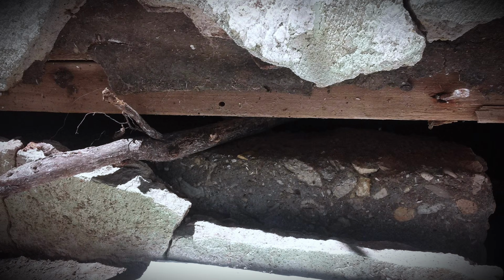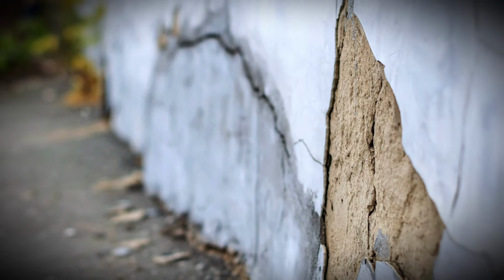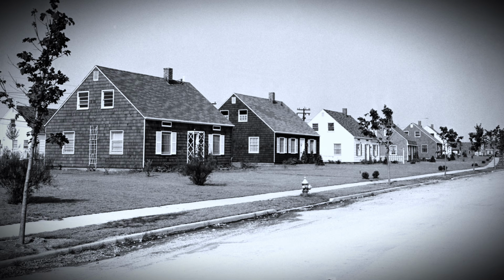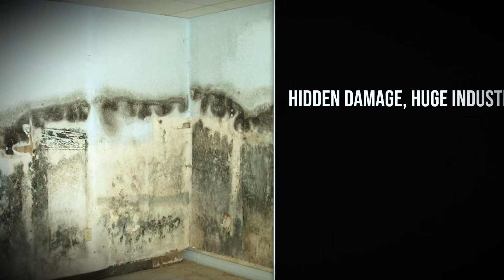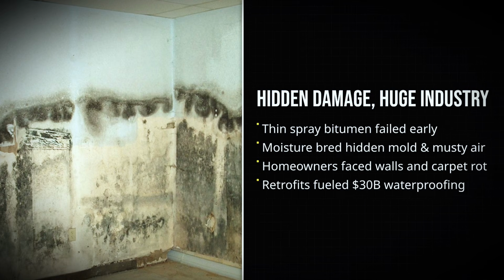That thin asphalt coating becomes brittle over time. It cracks, it peels. Soil settlement creates voids. Tree roots push against it. And within 10 to 20 years, many of those foundations were letting water in. Not immediately, and not dramatically, just slow seepage, damp walls, musty smells, mold growing behind finished drywall that nobody can see.